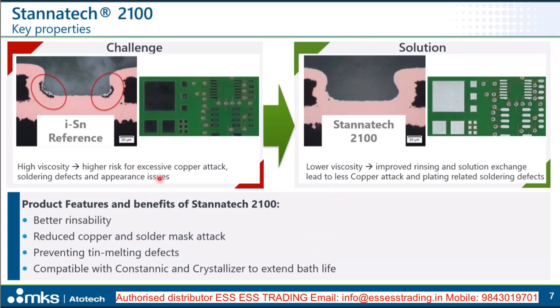A brief key summary of the benefits of the Stannatech 2100. There are, as mentioned, certain risks for the existing immersion tin processes, which are connected to the very high viscosity that immersion tin plating solutions have. The high viscosity causes two limitations. You have a poorer solution exchange, so you need to really take care, also equipment-wise, to bring fresh solution to the surface, and in particular in narrow features, the solution exchange might be poor, leading then to excessive copper dissolution in the edges, causing corrosion, which is unwanted.